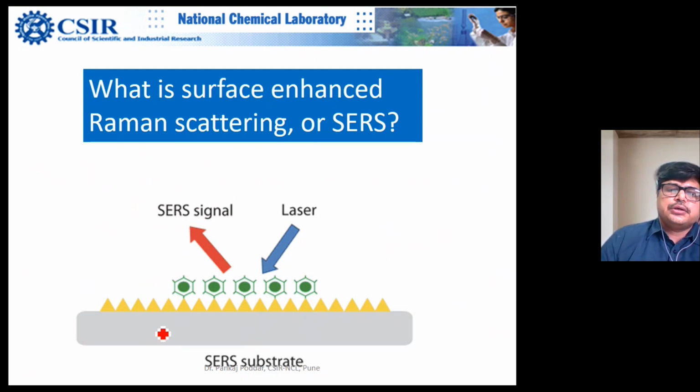Normally people take silver or gold or sometimes aluminum systems with different custom-made substrates. The pointed edges are much more beneficial, for example, star shape. The resonance frequency will depend upon the dimensions of the roughness and also the shape of these rough edges.